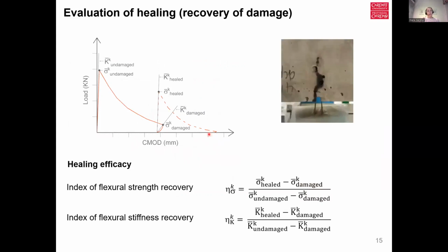And then we have our evaluation of healing. So this is really setting the scene for how we're going to report our healing. We have two healing efficiencies that we report: our index of flexural strength recovery and our index of flexural stiffness recovery. So we have our typical load-CMOD loading cycle, at which point we have our peak load. We then carry on loading until we get to our desired crack width.